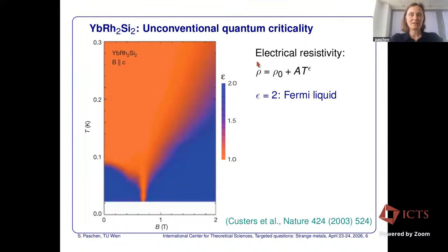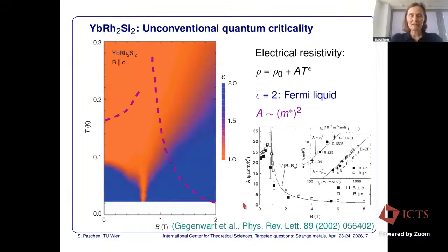So you see this is the temperature dependence that all the data are fitted to across the temperature ranges for different magnetic fields. And if the exponent is 2, you see blue here. Interestingly, even the blue is interesting. The A coefficient of the T-squared resistivity is very strongly enhanced when you move towards this point here. That means that the effective mass appears to be strongly renormalized towards the critical point, up to the point that it is consistent with a divergence from both sides of the quantum critical point.